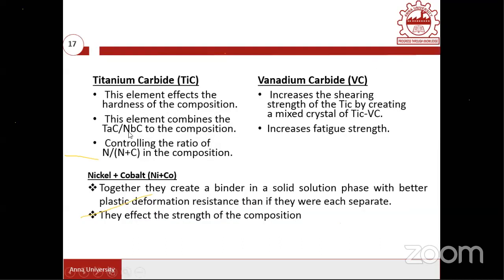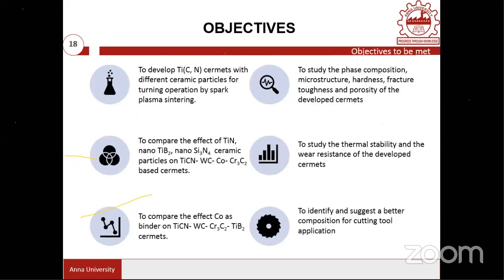And titanium carbide is a good material for hardness improvement. And vanadium carbide is going to increase the fatigue strength. And nickel plus cobalt is basically going to assist the binding activity. So all these elements are very, very important. And if you understand the basic core-rim structures, you are able to play with the microstructures and then modify the mechanical property.